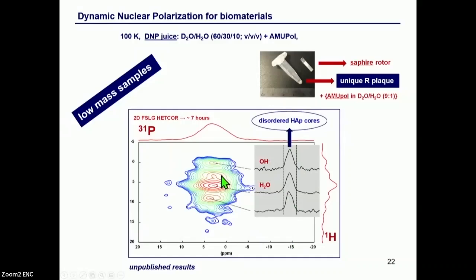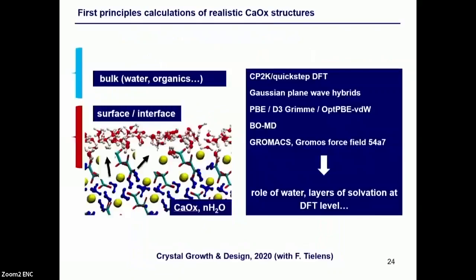And from the structural point of view, it's important to us because it was the first time that we demonstrated that, yes, indeed, it is an apatite. The Randall plaque is an apatite, but to our surprise, the cores of the apatitic structure are highly disordered, much more disordered than cores observed in teeth and bones.